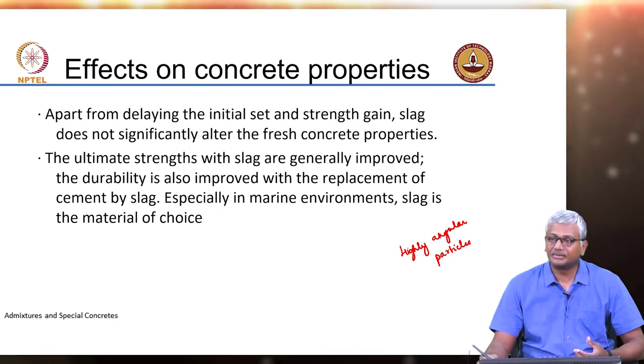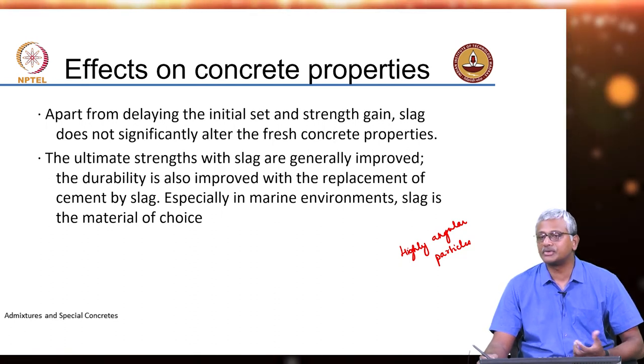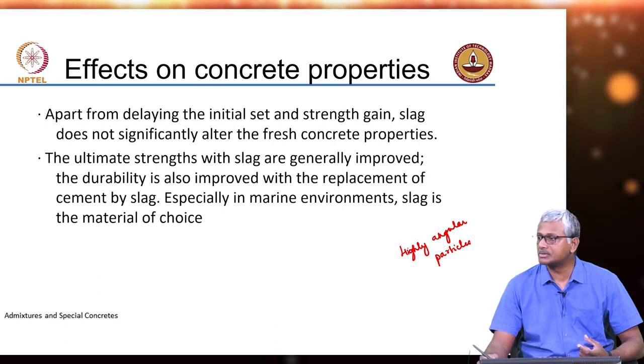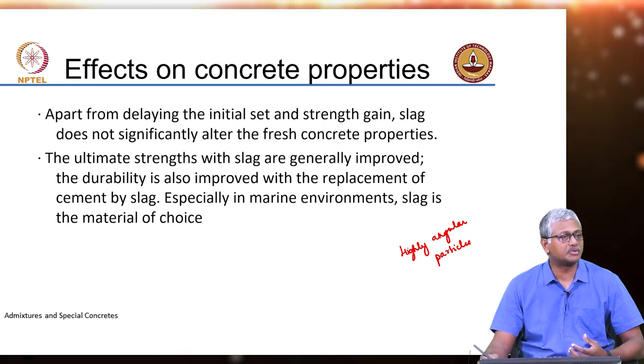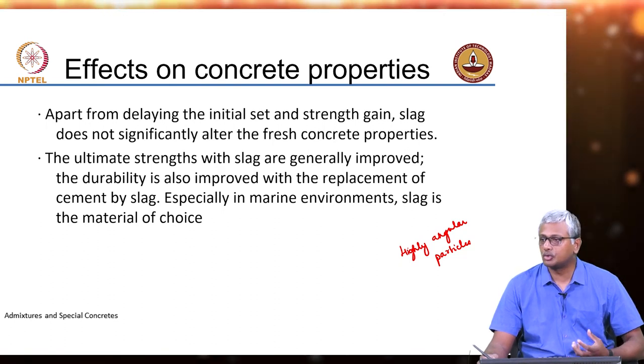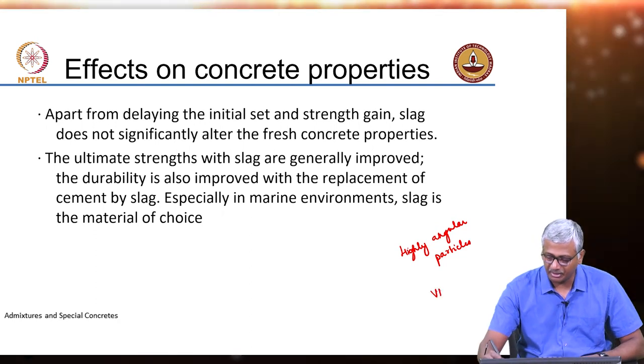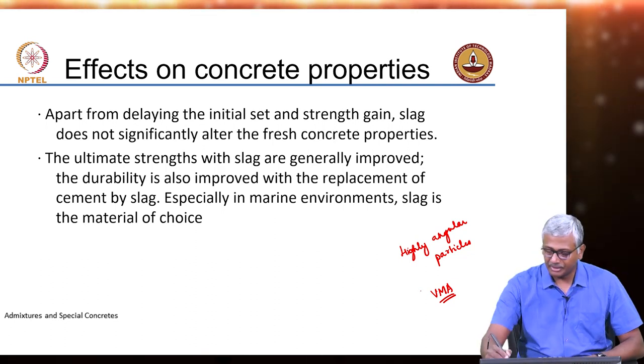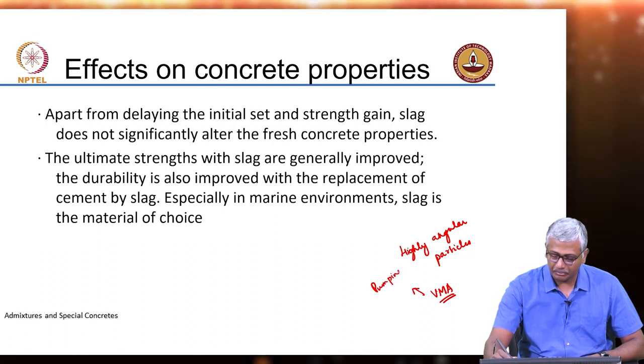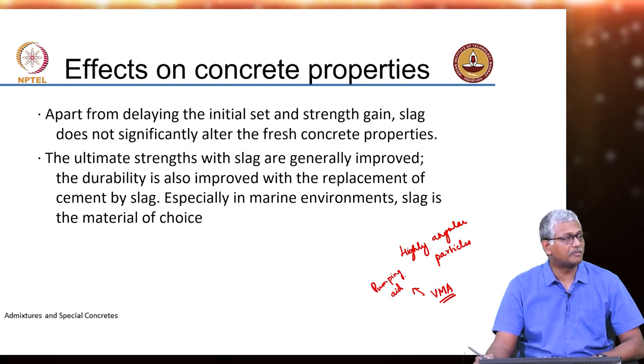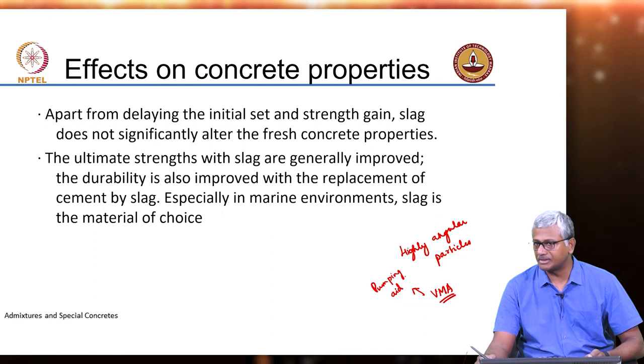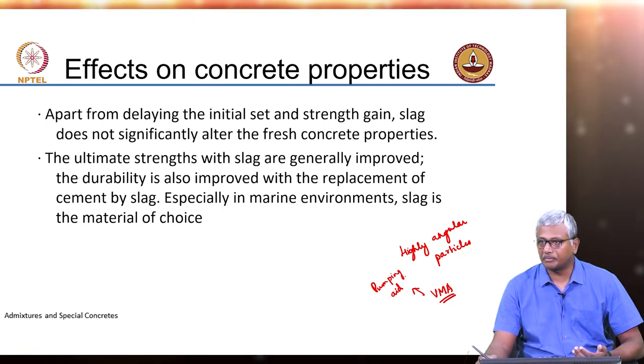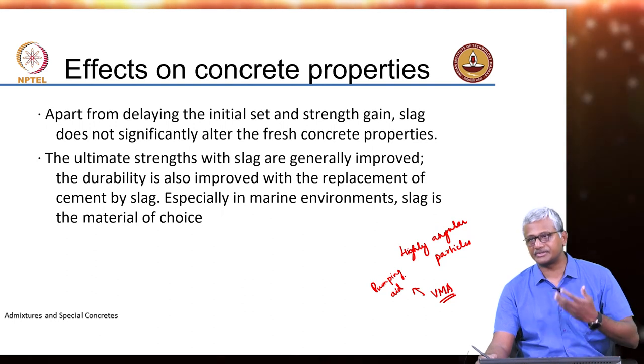So that is one thing to keep in mind. When trying to use slag concrete for pumpability, try to design it with a slightly higher slump so that you can reduce this extent of wear and tear on the pipe. Alternatively, we can use an admixture — if you want to push concrete easily through a pipe without too much resistance, a viscosity modifying agent, VMA, can be used. VMA is also known as a pumping aid. So slag concrete is difficult to pump because of increased wear and tear of the pipe due to hard slag particles, and you can make it easier by designing with a higher slump or using a VMA.